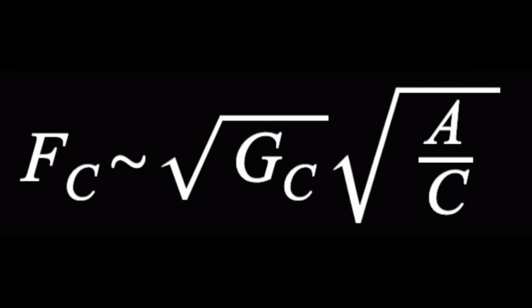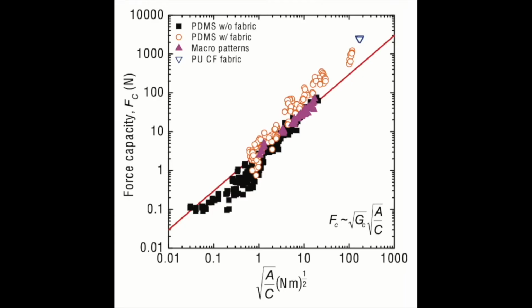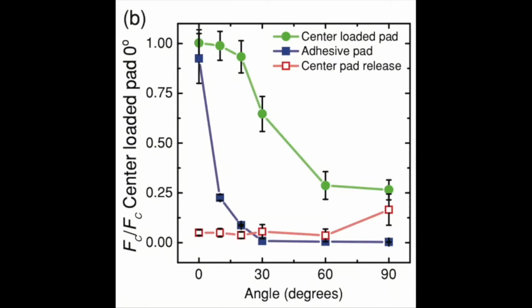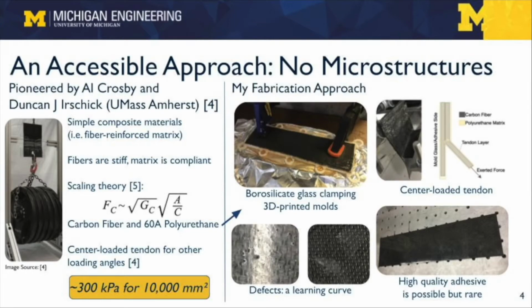A third parameter in the scaling theory, G sub c, is a property of the interface between the adhesive and the adherent. It was found in the research done at UMass Amherst that the highest performing adhesive was comprised of a polyurethane matrix with a hardness of 60 Shore A and carbon fibers reinforcing it. Additionally, it was shown that adding a rigid tendon to the center of the adhesive pad so that all of the adhesive force is transferred through it increases the force capacity at loading angles other than 0 degrees to the surface. So I implemented this in my design as well.